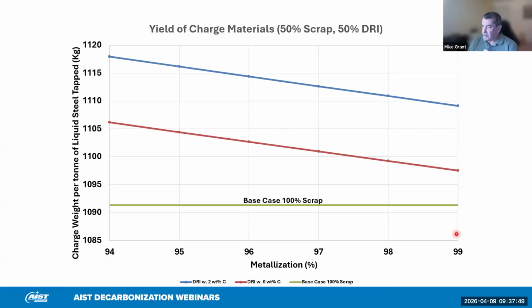Now, this is the amount of material that you need to charge into the furnace to get 1,000 kilograms of steel out of the tap. And you can see that a highly metallized DRI has much more metallic iron in it, much less oxygen, and so the total weight that you charge can be much lower compared to 94% metallized, where you have a lot of iron oxide, FeO, in the DRI product. In order to make up for the oxygen contained in your DRI, you have to increase the weight of the charge. This is a pretty simple principle. Of course, if we have 2% carbon, as we're doing in this comparison, we see that the charge weight's even higher compared to the 100% scrap case.